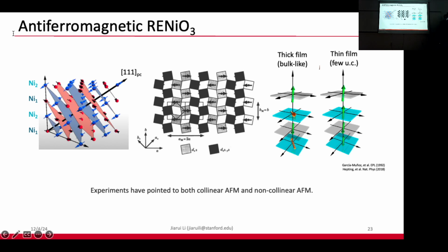And the magnetic structure of this compound has been studied since the 1990s by neutron diffraction, and they pointed out that it should be a collinear magnetic structure, where it should be up, down, or left, right. That nickel 1 and nickel 2 are all parallel, in line with each other. But later on, more and more studies have discovered that it could be non-collinear, where these 2 spins can add an angle.